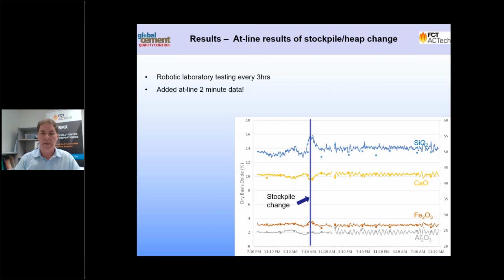But what I've done here is I've added the 1 to 2 minute data from the online XRF machine and superimposed it with the lab results. And what you can see here is that there's a lot more information that can be gathered. So we're presenting here 3 days worth of information sampled, as I said, every couple of minutes. And so it's very obvious where the pre-blend heap changes occurred. The silicon has shot up and then it's come back down again as the reclaimer has moved into that heap.